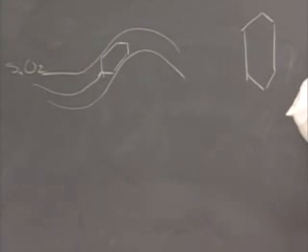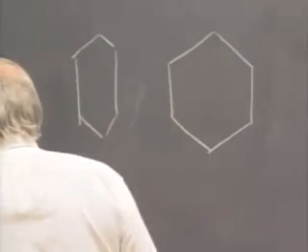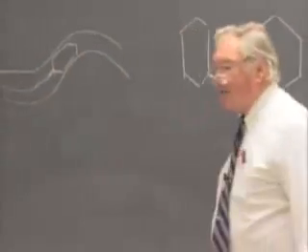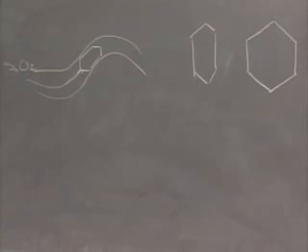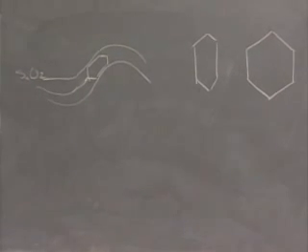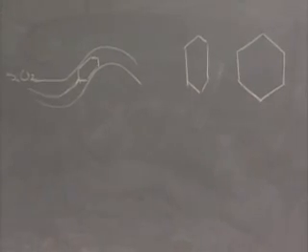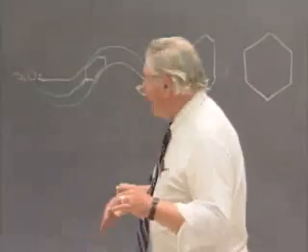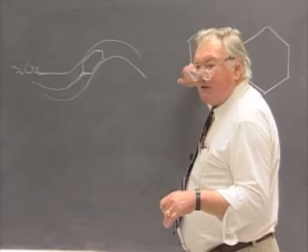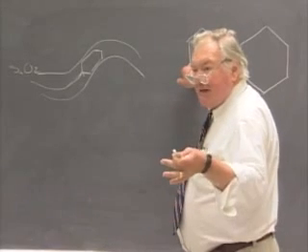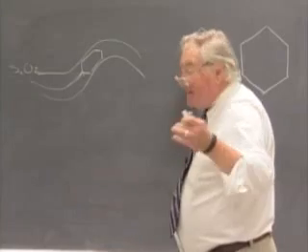Doesn't appear to be anything hexagonal about it. But what's happened is this crystal, if it had developed in a uniform environment, would have had a hexagonal shape. But because the nutrients are flowing in from one direction, it tends to elongate in that direction. So how could you assign the symmetry to that crystal that you dug out of the rock? Unfortunately, crystals do not come with a legend on the bottom that says quartz SiO2 space group P3 subscript 121, made in USA. You have to yourself assign the symmetry.